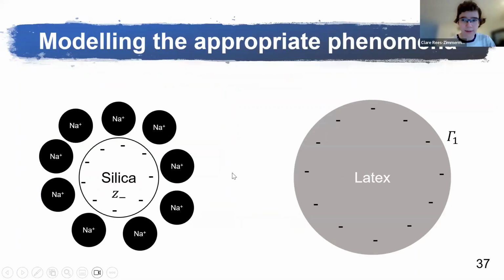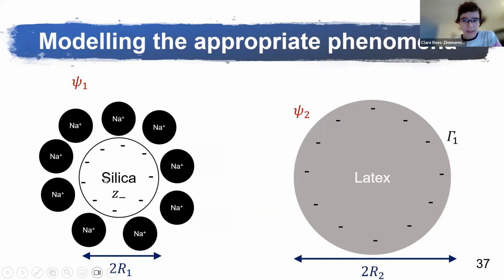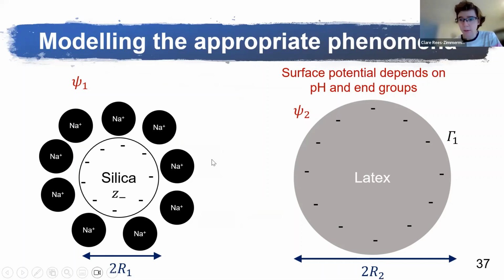And I want to go back to the question of modeling the appropriate phenomena. This is the kind of picture that I had. The silica and latex particles have certain radii, which we could vary. And they also have surface potentials. And these surface potentials depend on the pH and the end groups, which we could also vary. Because these are nanoparticles, we may also want to include other interactions, such as van der Waals interactions, which we may find to be important.